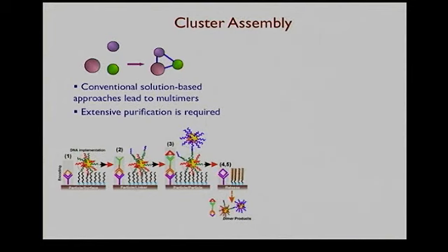More than that, when this particle comes and connects here, it will grab all available connections such that any other particle will not be able to connect. This is a quite simple approach which can remind many of you of either layer-by-layer deposition or solid phase chemistry, with a twist that the recognition of every new element is encoded with recognition of the previously already placed element. We can remove those simplest clusters, dimers, from the surface, and we end up with this type of dimer. It's the simplest cluster which already has useful properties, which I will show you immediately.